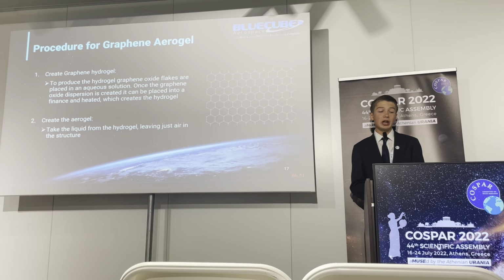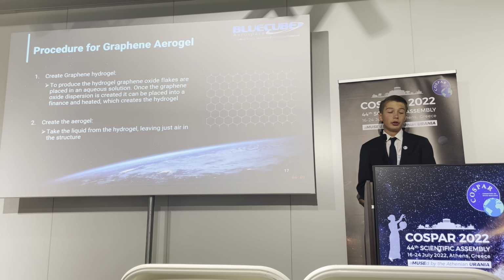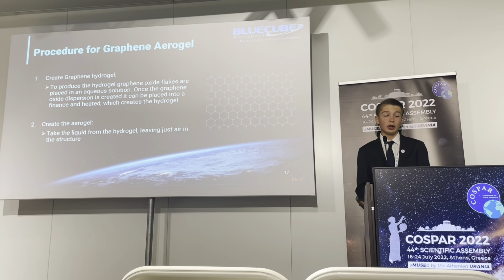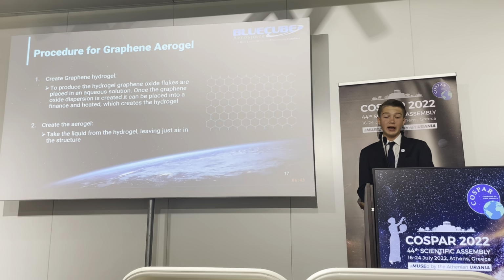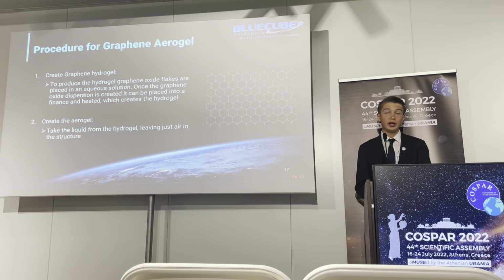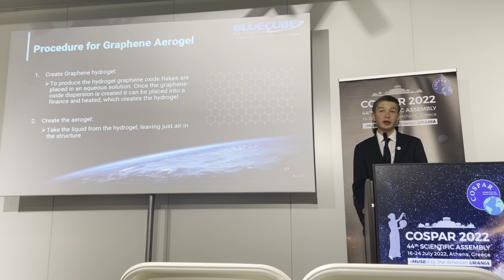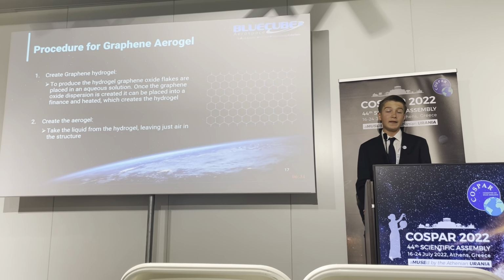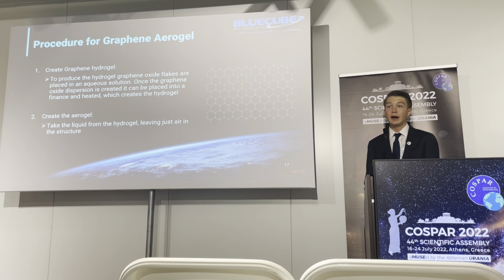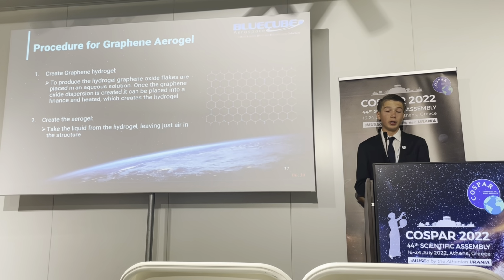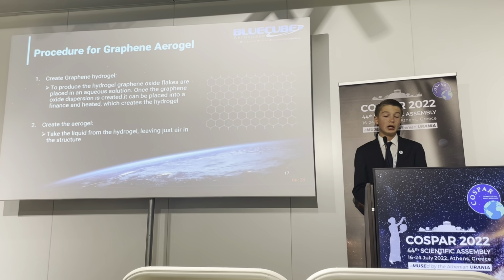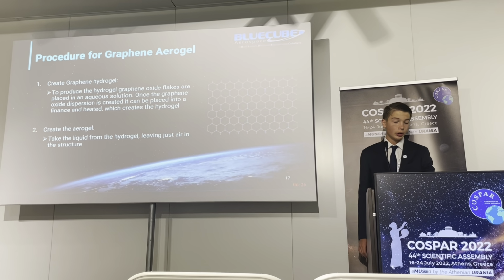There are 2 primary steps in creating graphene aerogel. The first is to create the graphene hydrogel. In order to produce the graphene hydrogel, graphene oxide flakes are placed in aqueous solution, and once the graphene oxide dispersion is created, it can be placed into a furnace and heated, which creates the hydrogel. And then to create the aerogel, the liquid component of the hydrogel is removed, leaving just air in the structure.